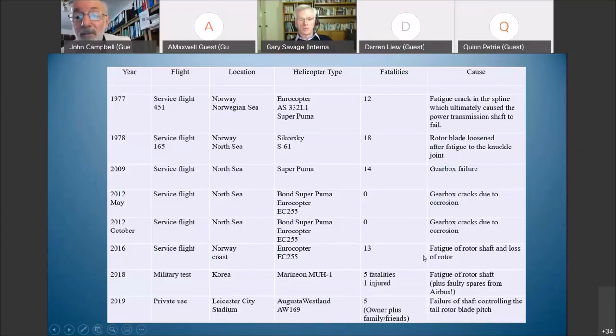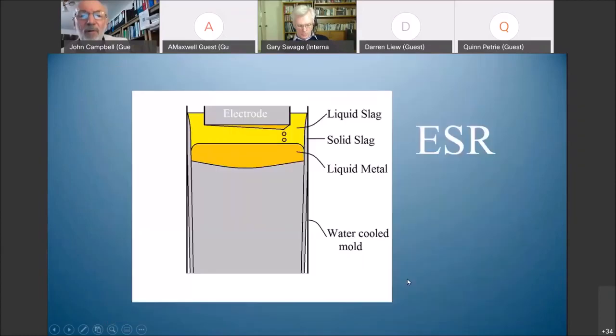And again, this was from a corrosion pit. No one could understand how you could get fatigue from a corrosion pit. But as soon as you realize that the pit is a sign that there's a bifilm underneath, then you realize what's happening. So these are very tragic, many of them. Nearly every one of them is a bifilm problem.